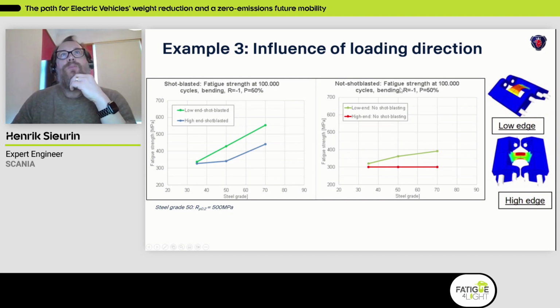If you have a non-shot-blasted material, for these high edge loadings, we see no influence. There's no point increasing the yield strength. It's the same. For the low edge, well, there is a slight increase. But if we introduce shot blasting, on the other hand, for the low edge bending, we have an almost linear increase in fatigue with the yield strength, and even for the high edge specimen, the influence of the shot blasting is really great.